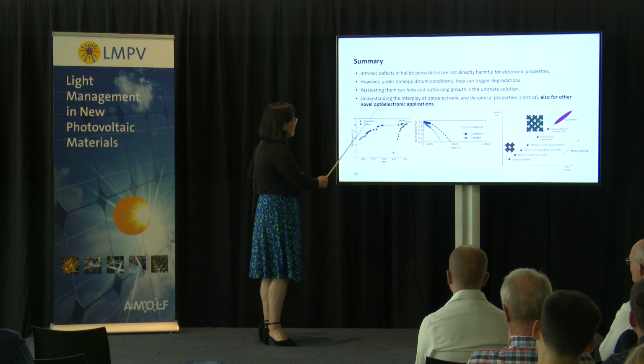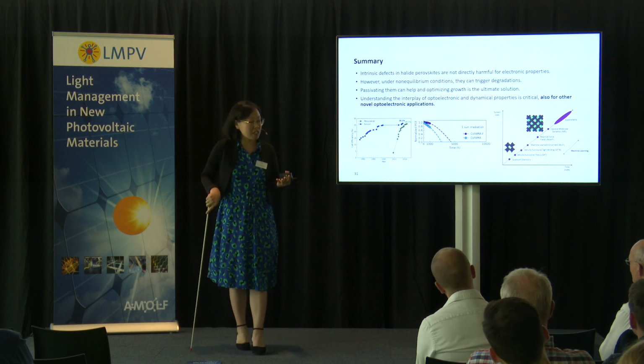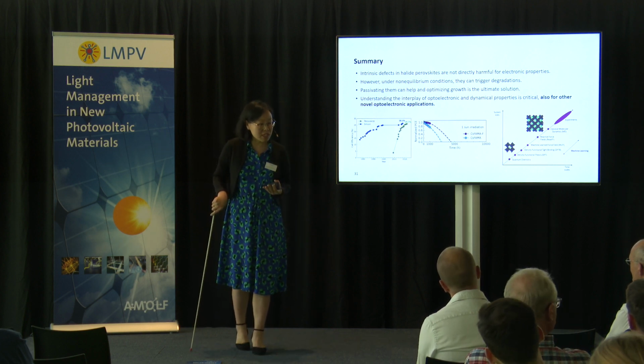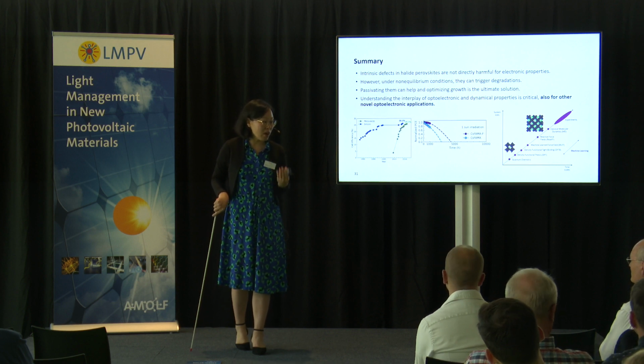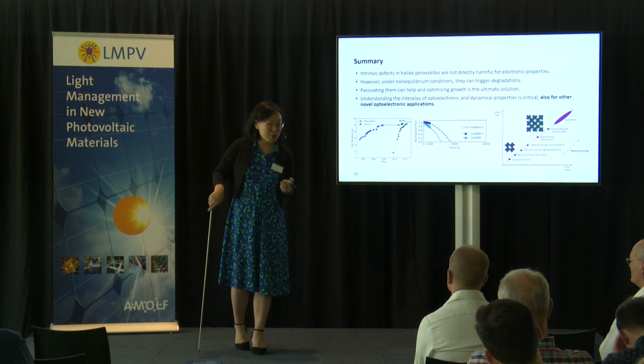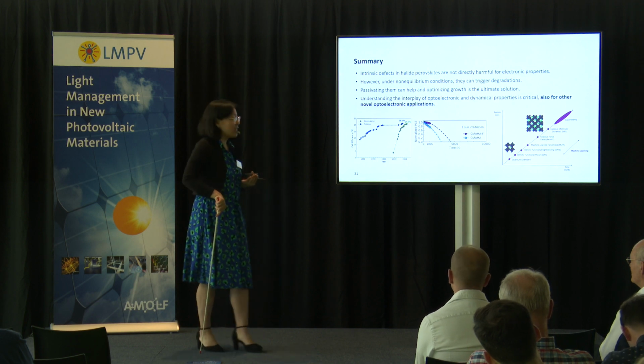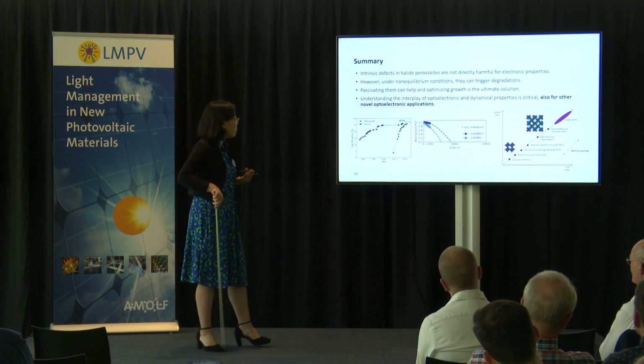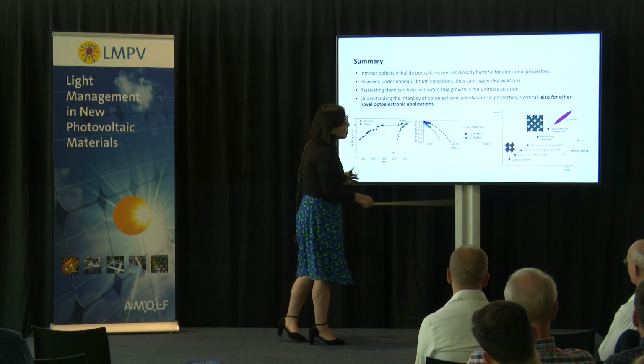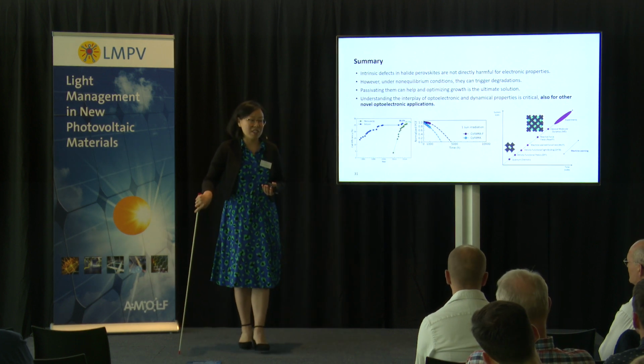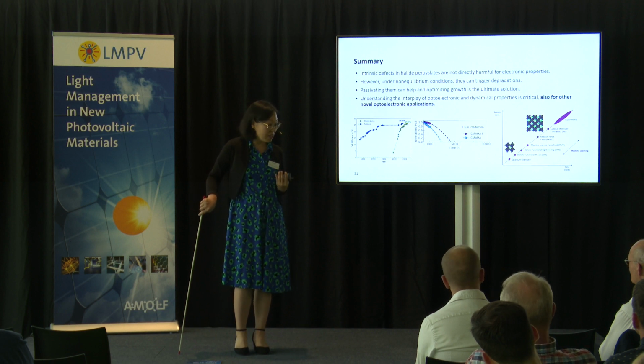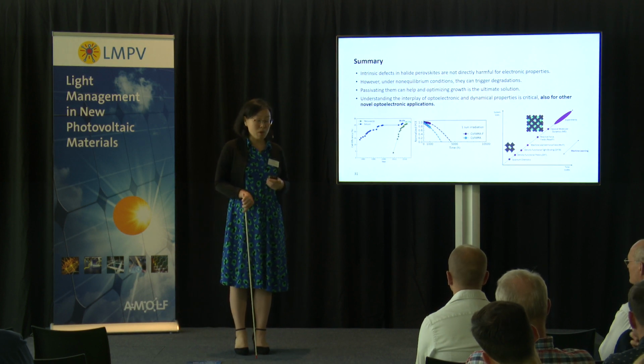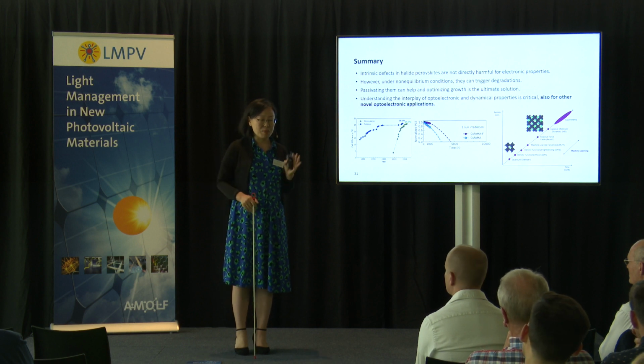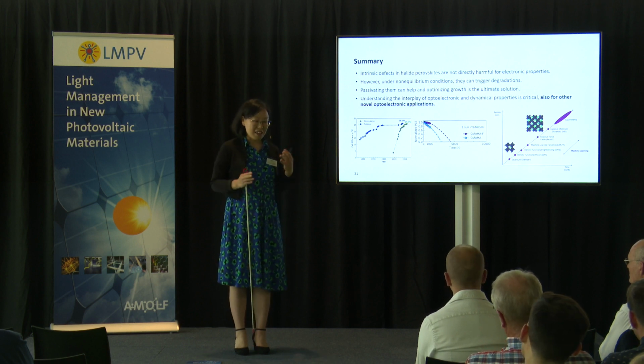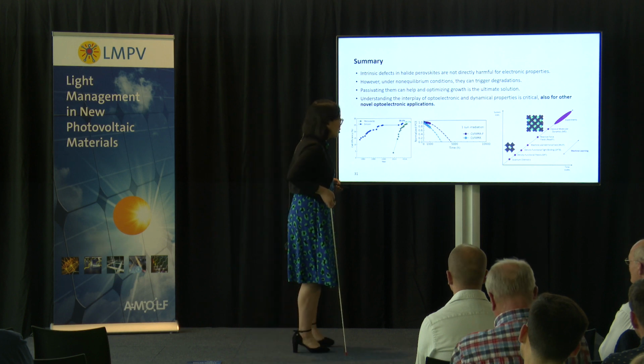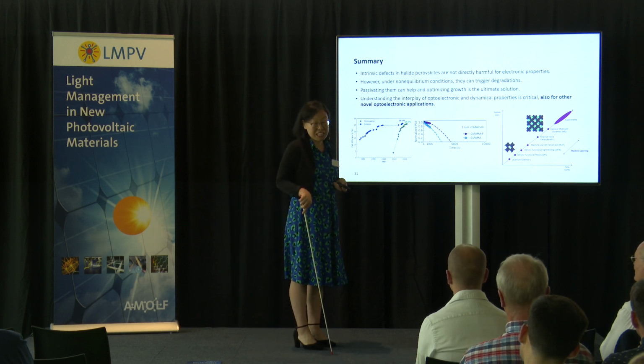But in the end, to actually grow a film or to actually make a stable cell, we need to get rid of all the defects, really to try to synthesize the most stable material without defects. Then the growth and the chemistry become very important. And I hope I also showed you that this fundamental study at the atomic or molecular level is very much complementary to the experiments and gives more insights, and every understanding pushes a little bit on the stability. I hope together with the community we contribute a lot in the next few years.